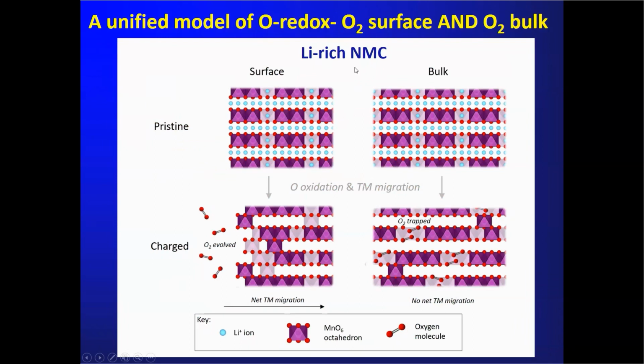So here's a representation of a lithium-rich so-called NMC, and this represents the surface and the bulk. And we're going from the top to the bottom here, to this region. We're oxidizing the oxide ions. So at the surface, what happens is you lose molecular oxygen, you get metals migrating into the vacant lithium sites, and you get this so-called densification process. The key thing here is, as you do this, you move the composition of this near surface region close to a stoichiometric composition. It's no longer lithium-rich, no longer oxygen redox active. And so this self-limits because of that, because once you've got a stoichiometric composition, then you've nothing to drive further oxygen loss and metal migration.